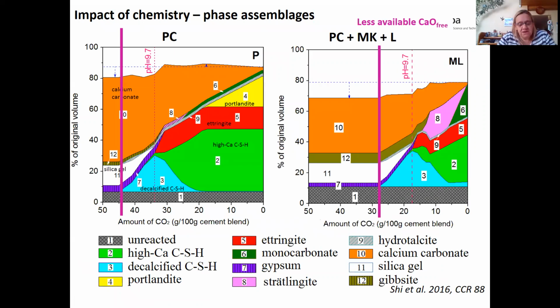When we now compare the changes caused by the carbonation of the two samples, here we have again the Portland cement, we can see that we carbonate until we reach a theoretical amount of CO2 of 45 grams per 100 grams of cement. If we do the same kind of calculation for the PC metakaolin limestone blend, we can see we can only add up to 28 grams CO2 per 100 grams of cement, basically meaning that the blended cements have a much lower CO2 binding capacity.